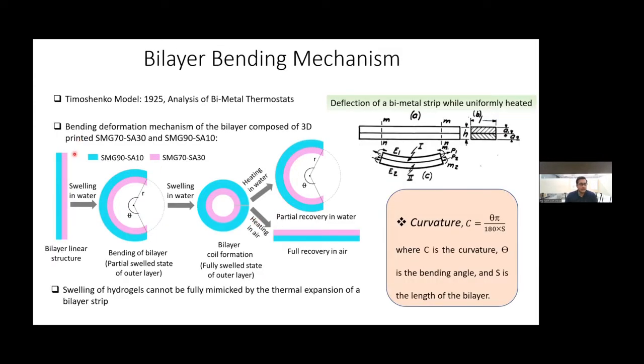And to make this bilayer, I have chosen SMG 90 SA10 as the outer layer, which has higher amorphous monomer concentration, and the inner layer made of SMG 70 SA30, which has higher crystalline monomer concentration. And when the bilayer is exposed to water, the outer layer absorbs water and tries to expand, and that's why it creates some stress in the mid plane, and that's why the bending happens. And here is the illustration of the bilayer coil formation, full coil formation. And we also have found the partial recovery in hot water and full recovery in air when heat is given.